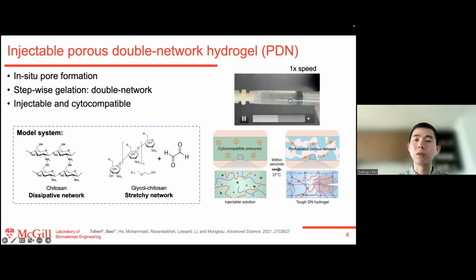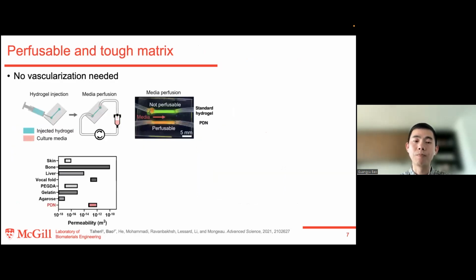And after the injection, because of the neutralization of the pH, the chitosan will phase separate from the solution, which you can observe from here. The color changes from transparent to translucent, which is caused by the phase separation of chitosan and forms a porous network within the hydrogel. And within the solid phase of the scaffold, the glycochitosan content will be further cross-linked by the dialdehyde groups to form a covalent cross-link network, which can further reinforce the mechanical stability. So in this case, we created an injectable, porous, cytocompatible, and tough hydrogel.